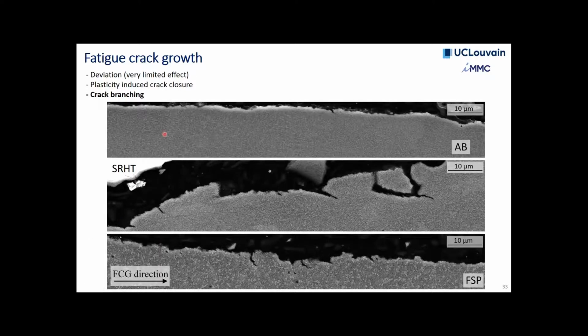And so here, as you can see, as built material, the crack is just sometimes deviating a bit due to the melt pool, but as I told you, in quite a minor way. But there is no branching. The crack is just going in its direction. While here in the stress relief material and also in the FSP material, what happens is you have some of the cracks that are branching, and this, of course, slows down this crack propagation.